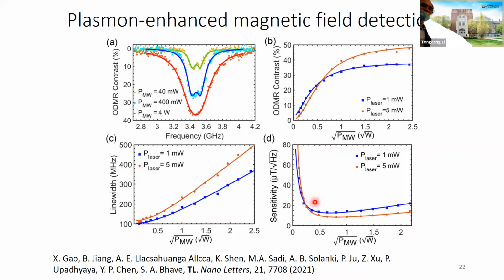But one thing I need to mention: in the older work, they have laser spots of 10 micron. In our case, we use a 100x objective to focus to the diffraction limit. So the spatial resolution also improved from 10 micron to about 500 nanometer. So we improved the spatial resolution by a factor of 20 and the magnetic field sensitivity by a factor of 10. So that's our work. And after we used this plasmon enhancement, now a lot of groups use the same scheme.